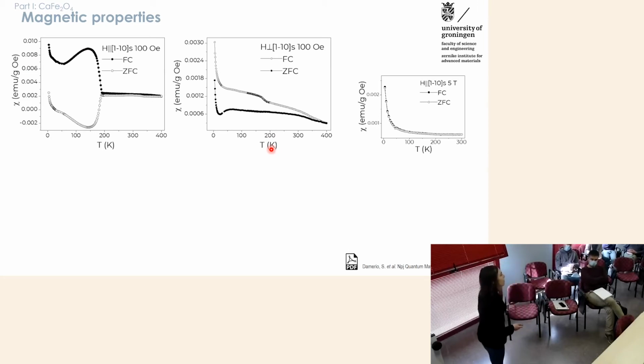So once we have these films, even though they are not perfectly single crystalline, we can already start studying them from the magnetic point of view. Because what is actually interesting is that for all these in-plane orientations, the magnetic easy axis, which is the B axis, would be along the long side of the needle crystal. So what we can do is first measure the magnetic properties when most of the crystal is oriented with the B axis parallel to the magnetic axis in the SQUID.